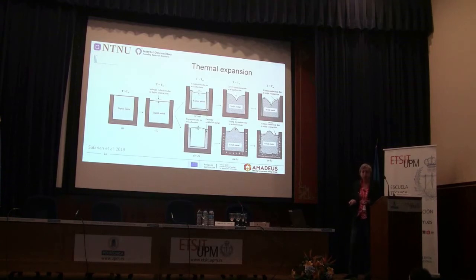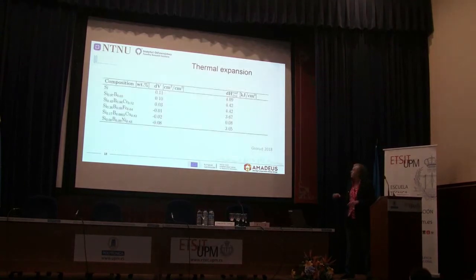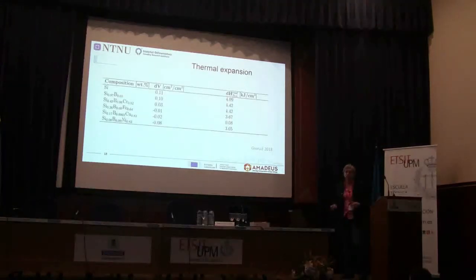So it means that we want to find an alloy which has a low or about 0 volume expansion during solidification, because we are not really looking for this either, and it can also produce a lot of pores up here, right? So we are really looking for something that keeps the delta V about 0. And when I'm talking about delta V here, it's not the propulsion that Matthew talked about yesterday, but it's the volume change. So we see here the different compositions.